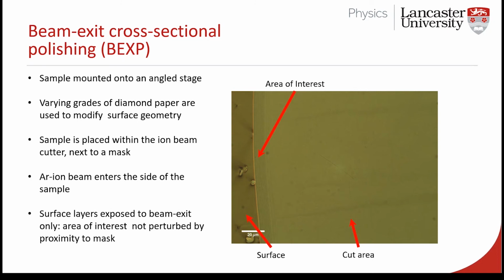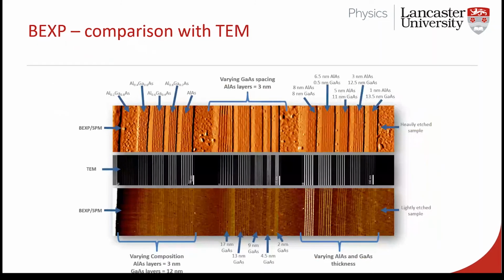Taken to an extreme example here, the final slide I've got from Alex, is a massively multi-layered structure of lots of little semiconductor layers that have been grown by various techniques. You can see through the middle here, the black and white image. This is the focused ion beam and TEM image. Very good, very high resolution, very expensive. Against the top is the topographical. This is the BEXP and the topography scanning probe microscopy. And at the bottom, BEXP and the mechanical scanning probe microscopy. So we can absolutely access all of those details, and in fact, far more information, because now we can do electrical characterization, we can do mechanical characterization, things you can't do with transmission electron microscopy on these cut samples.